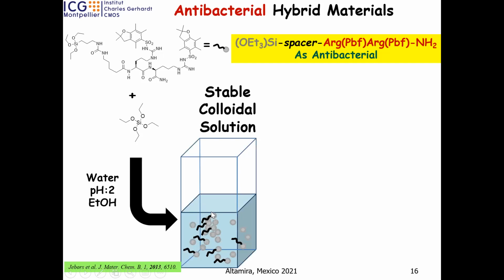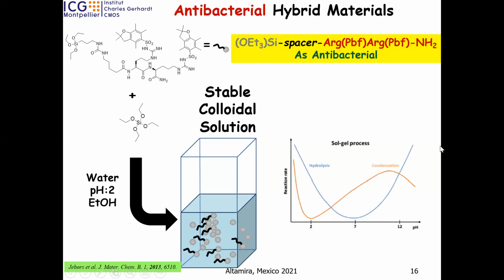So we prepare a colloidal solution. You put it in your mixture of water and ethanol at pH 2. At pH 2, you have a stable colloidal solution. This colloidal solution can be stored for 3 months or 6 months without any problem. Why? It's stable. If you see here, you have the kinetics of both reactions, hydrolysis and polymerization. The hydrolysis doesn't take place at pH 7. Since we are at pH 2, the hydrolysis is very high. However, if you can see the condensation, the cross-linking, the reaction between two SiOH to make a siloxane bond, it's very low.